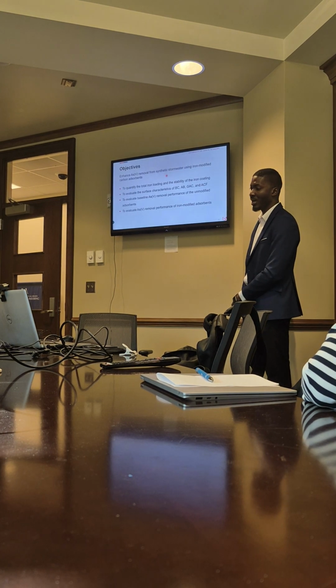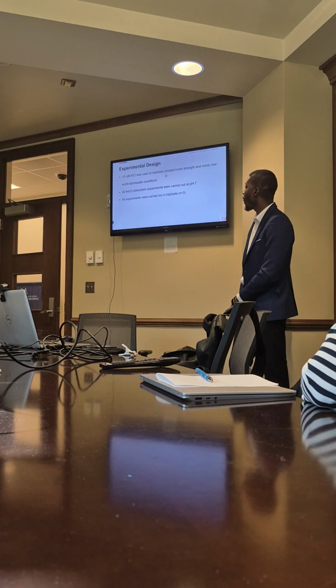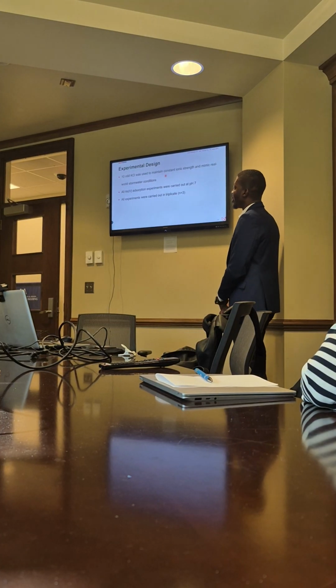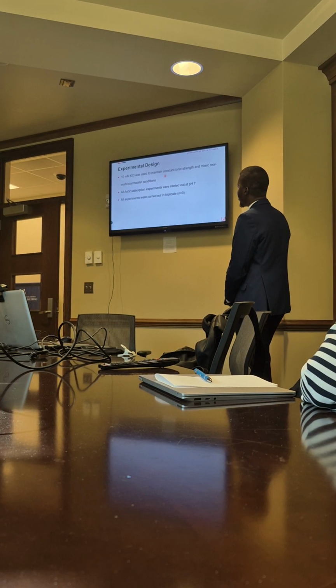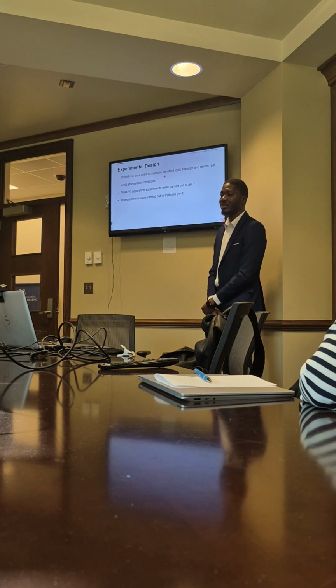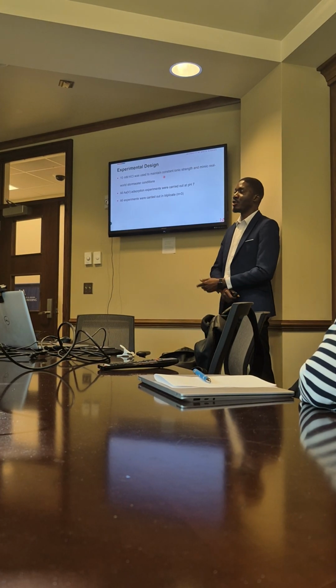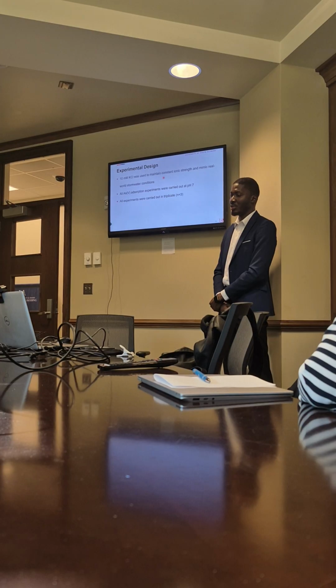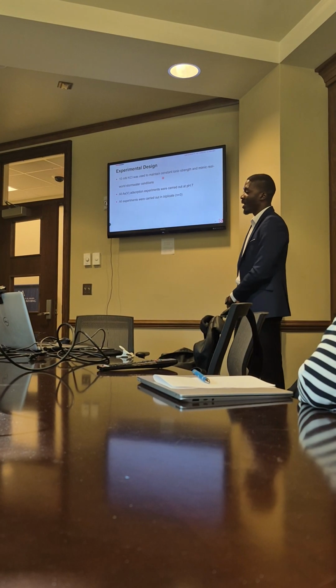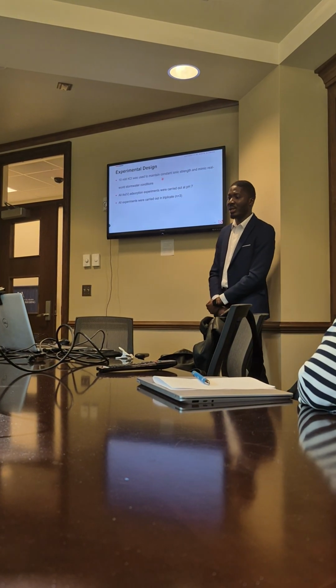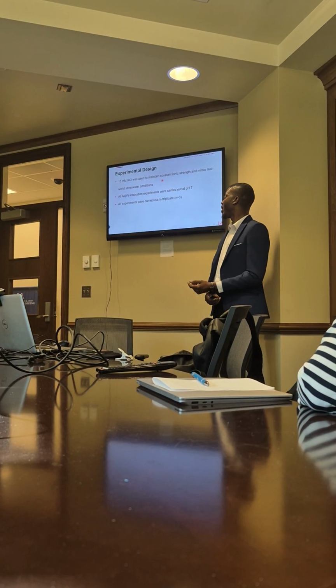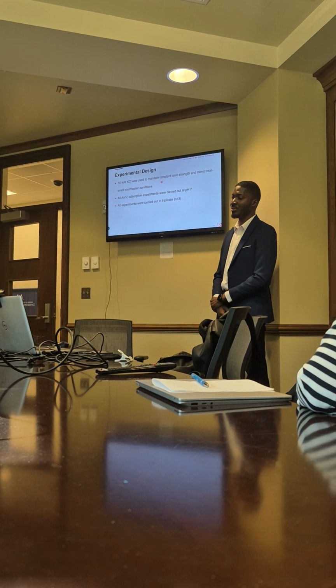So with our experimental design, we are going to use 10 millimolar KCl to maintain constant ionic strength because KCl can also mimic our stormwater as well. Secondly, all our arsenate removal experiments were carried out at pH 7 and all our experiments were also carried out in triplicates.